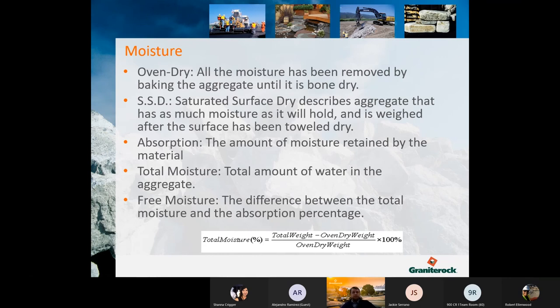Oven dry moisture means that all moisture has been removed from the aggregate. Saturated surface dry describes aggregate that has as much moisture as it will hold. However, the surface is dry or towel dried. Absorption is the amount of moisture that a rock can hold. Total moisture is the total amount of water in the aggregate. And free moisture is the difference between total and absorption. So we take this into account, like I said, when we're batching to make sure that the correct amount of water and weight is going into the mix.